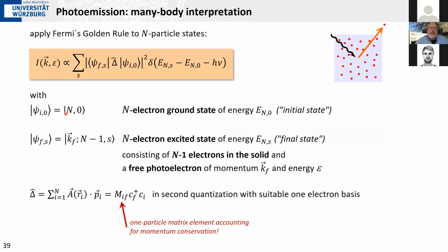So my photoemission intensity as a function of momentum and photoelectron energy epsilon, again, is written here as a matrix element squared. I have an initial state. This is simply the ground state, the n-electron ground state of our system, all n electrons sitting in their ground state. And I have a transition matrix element, which is this A dot P term that we had before, but now applied to all my n electrons in the system.